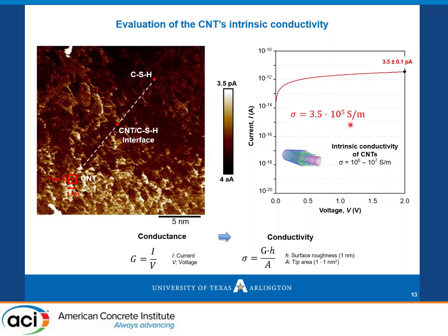And we correlate the value that we obtained with the nominal intrinsic conductivity that was provided by the manufacturer of the CNTs. And you see here that our calculated conductivity is very close to the nominal intrinsic conductivity of the nanotubes.